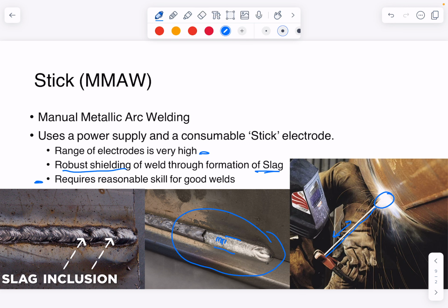And so undercut in that case, if I can draw that, right, that's my beaut weld. If I had undercut, I might actually have a divot on either side of that where I've not put enough metal in, and I've weakened it because that section thickness is now thinned. So there's no evidence of undercut, there's no evidence of slag inclusions. And if you do this right, you touch the slag with a chipping hammer and it pretty much just falls off.